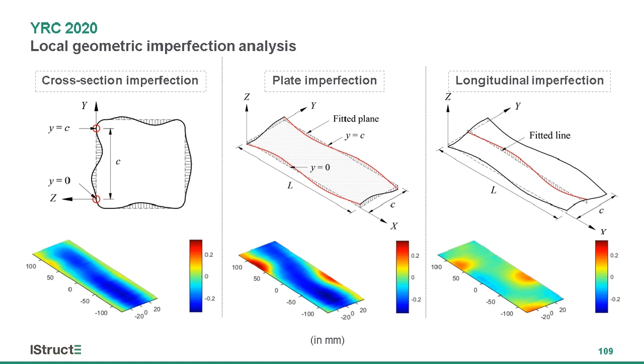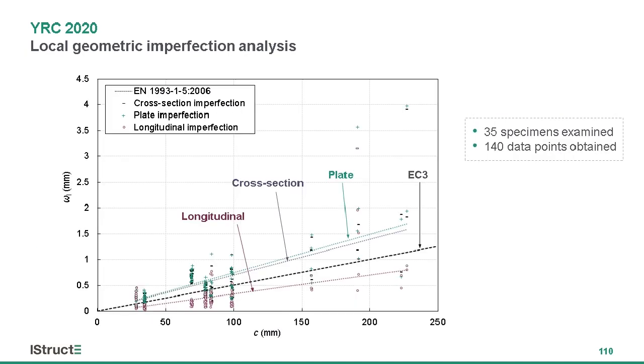Typical results are shown, and we take the maximum deviation as the local imperfection amplitude. If we plot the measured values against the width of the flat region, we found that the longitudinal imperfections are on average lower than the other two methods, and also lower than the Eurocode 3 recommendations.